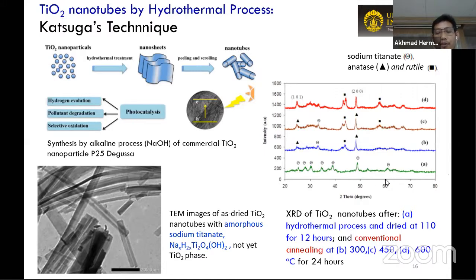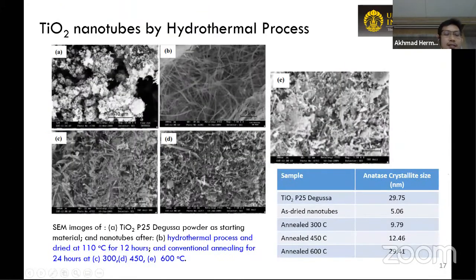So by increasing the calcination or annealing temperature from 300 degrees Celsius to 600 degrees Celsius, we find the anatase and rutile crystalline phases of the titanium oxide. So we can consider that in terms of crystallinity, it is successful. But based on the SEM image, next slide, please. Yes, this is the scanning electron microscopy image, with A being the TiO2 P25 Degussa as the